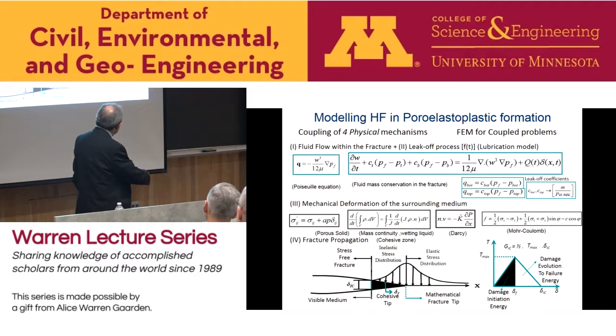We did also some sensitivity analysis on how the results depend on this cohesive model. And we found that the loading path, as we call it, the elastic path, affects the results, actually affects the development of the process zones. The exact shape after the peak, which expresses the damage of the rock, the splitting of the rock, doesn't affect the results much. But the loading part affects a lot the process zone and the results.